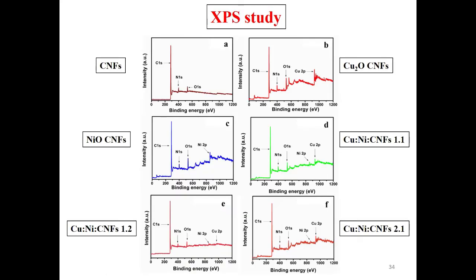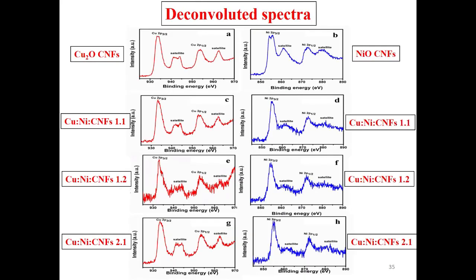These are the XPS studies of all the nanomaterials we have synthesized: cuprous oxide, nickel oxide, and copper nickel carbon nanofiber from the ratio 1:1 to 2:1. This is the deconvoluted spectra. The deconvoluted spectra show a tremendous change in the binding energies with the change in the ratio of copper and nickel, and after carbonization the effect is very effectively observed in this particular material.